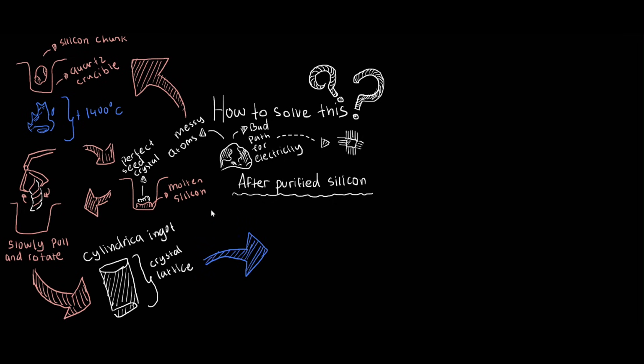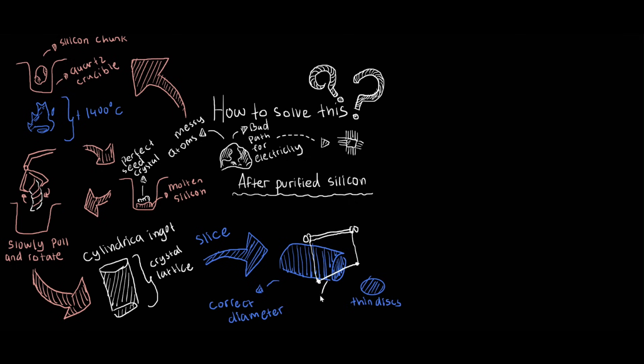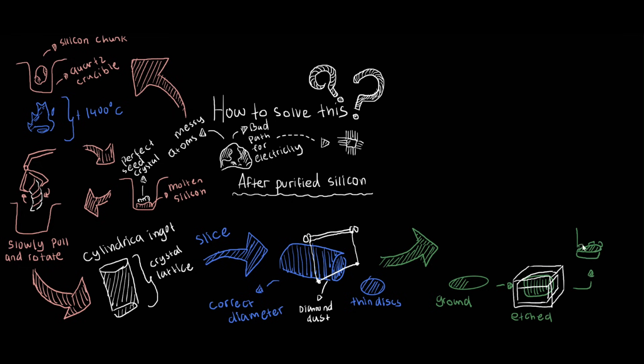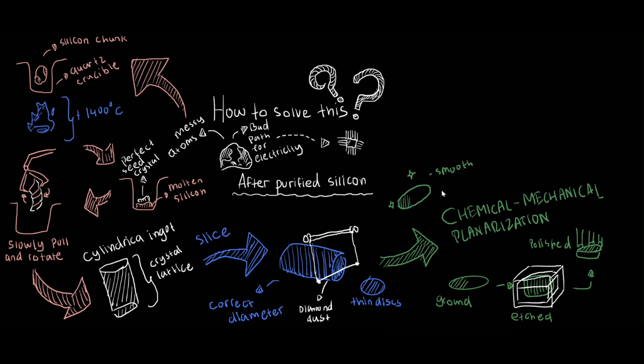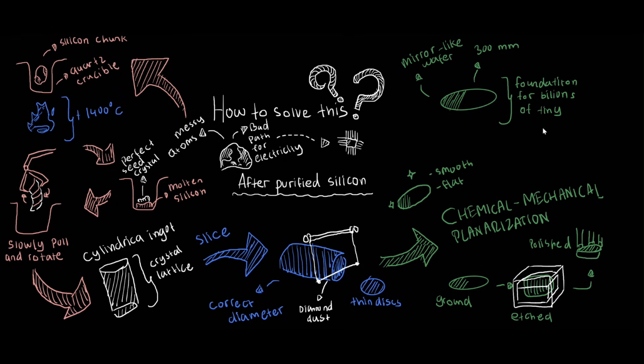When this heavy crystal ingot is grown, it is trimmed to the correct diameter and then sliced into thin discs using a precision wire saw embedded with diamond dust. These raw slices are then ground, etched, and polished using a technique called chemical mechanical planarization until they are flawlessly smooth and flat. What we are left with is a mirror-like wafer, usually 300 millimeters wide, which serves as the pristine atomic-level foundation upon which we will build billions of tiny transistors.